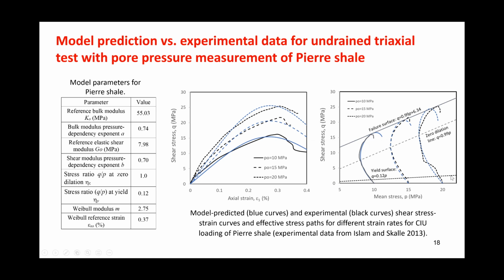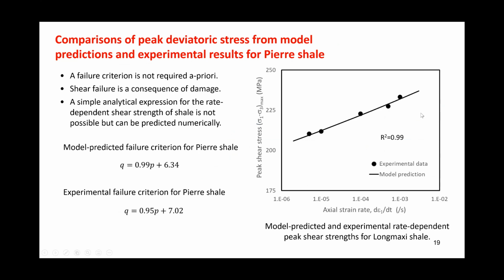Okay, the yield surface is linear, as I showed a while ago. The zero dilation line is also a straight line with zero cohesion. And the failure surface from the peak, I can show this to you. This can be predicted by the model as well. This peak failure surface was not prescribed a priori, which is linear. So again, like in the previous model for the total stress, a shear failure criterion is not necessary. It comes out as a result of damage.